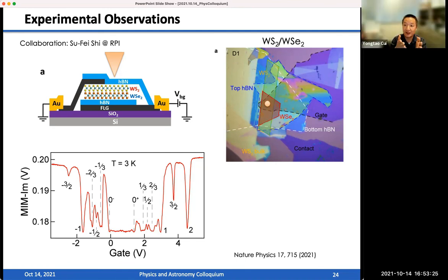Actually, in this Moiré system, in the Wigner crystals, in the 2D-based Wigner crystals, people have regarded this microwave frequency response as a signature of the Wigner crystal, because when the electrons are localized, they form local vibrations, and that frequency mode is in the gigahertz regime. But I think in our case, we don't have any signature of that yet.